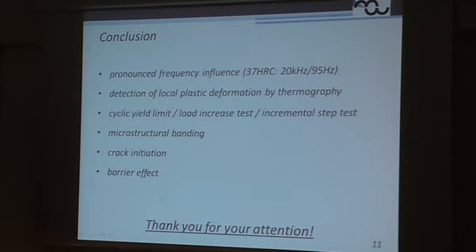So let me sum up my talk. What we can observe is that we have a pronounced frequency influence on our martensitic material. The detection of local plastic deformation by thermography was shown, and this is possible. The cyclic yield limit could be obtained by a load increase test and also by incremental step tests. The influence of microstructural banding was also shown by the thermography, and crack initiation was found even at a high number of cycles, but the surrounding microstructure acts as an effective barrier against fatigue crack propagation in the very high cycle fatigue regime.